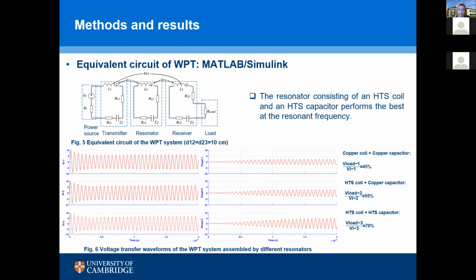Figure 6 plots the voltage transfer waveforms of the system assembled with different resonators. The left half is the input voltage, and the voltage on the load is on the right half. We calculated the ratio of the amplitudes of the two ports' voltages. It shows that while the HTS coil in the resonance has improved the efficiency from 45% to 55%, the HTS coil working with an HTS capacitor in the resonance can further increase this figure up to 70%. That is to say, the all-superconducting resonance performs the best at the resonant frequency.